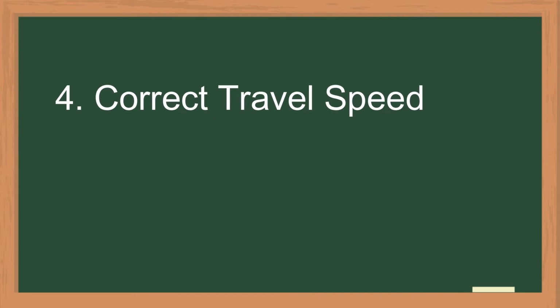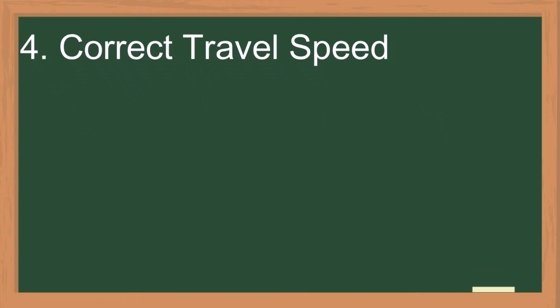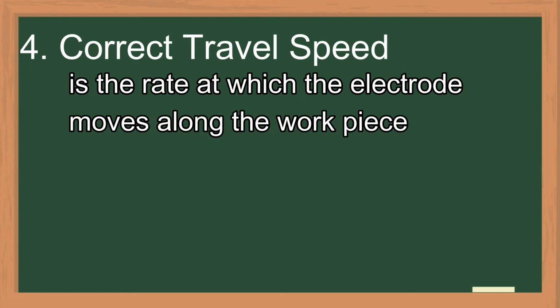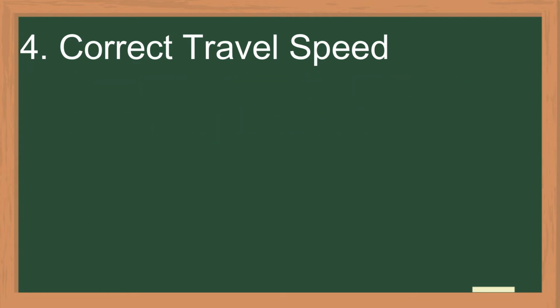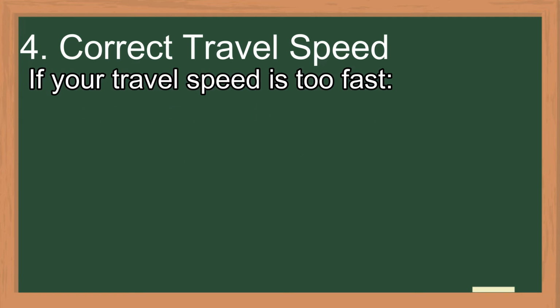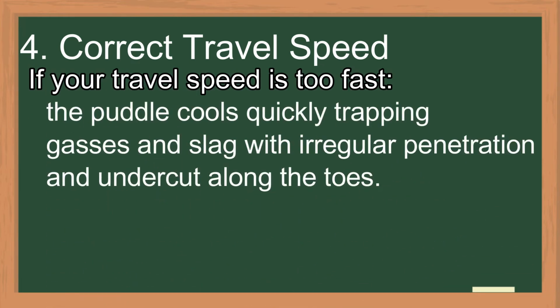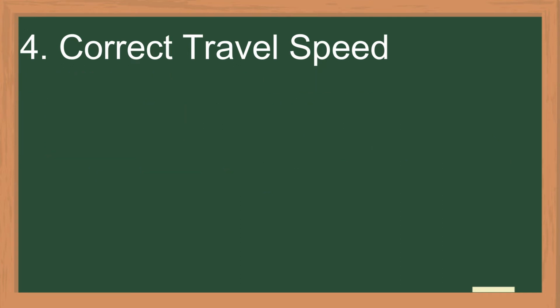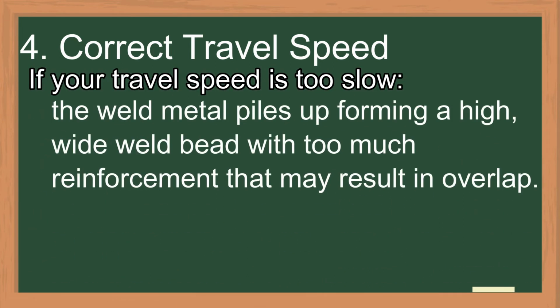Number 4. Correct travel speed is the rate at which the electrode moves along the workpiece. If your travel speed is too fast, the puddle cools quickly, trapping gases and slag, with irregular penetration and undercut along the toes. If your travel speed is too slow, the weld metal piles up, forming a high, wide weld bead with too much reinforcement that may result in overlap.